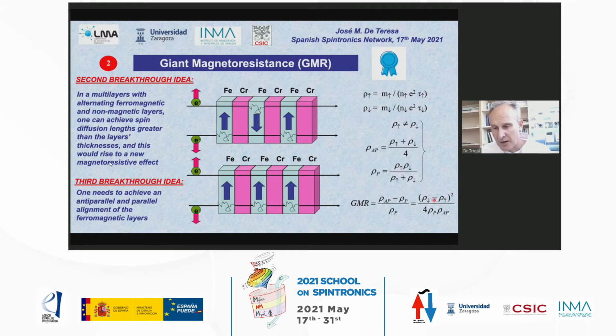And the important parameter here is the square of the difference between the resistivity of the spin down channel and the spin up channel. So if you are able to prepare these layers and to obtain this antiparallel configuration, you will obtain a giant magnetoresistance effect. But then we needed a third breakthrough idea. And the third idea was to be capable of achieving an antiparallel and a parallel magnetic configuration.